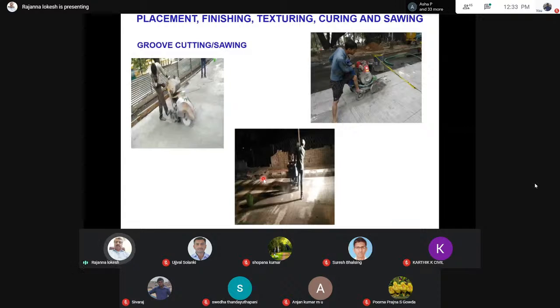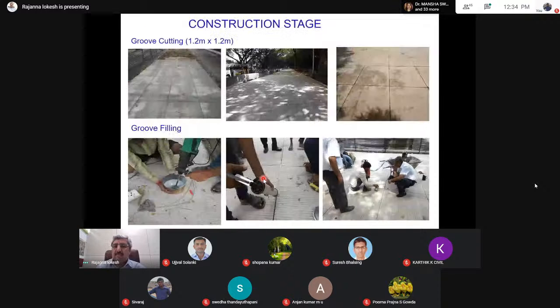So groove cutting shall be carried out for both longitudinal as well as transverse. The time for groove cutting is once again dependent on the strength of concrete that is achieved after 8 hours or 10 hours. So it is better that we examine the stretch after 8 to 10 hours, and then take a call whether the groove cutting can be carried out or not. In all possibility, around 8 to 10 hours, the groove cutting should be started.